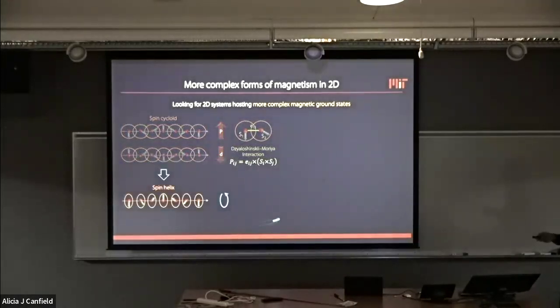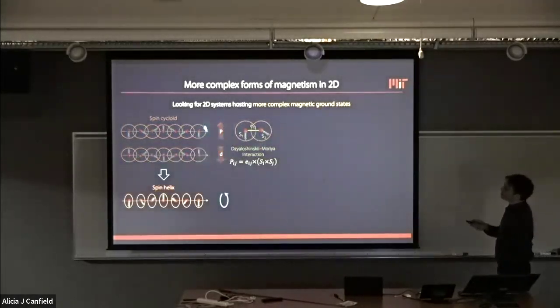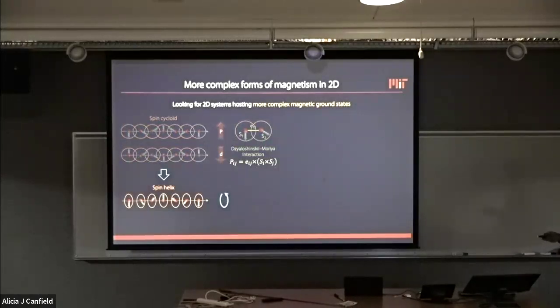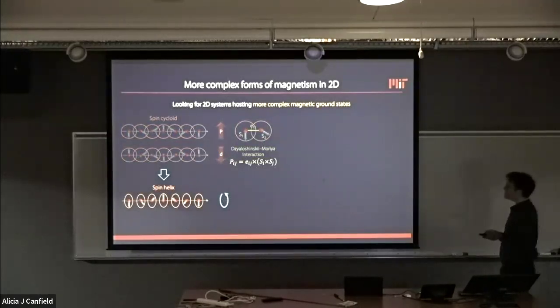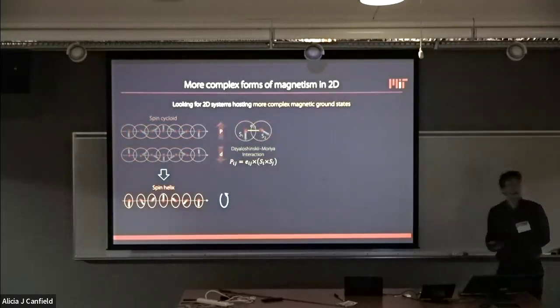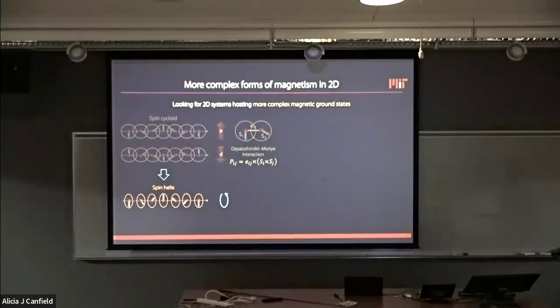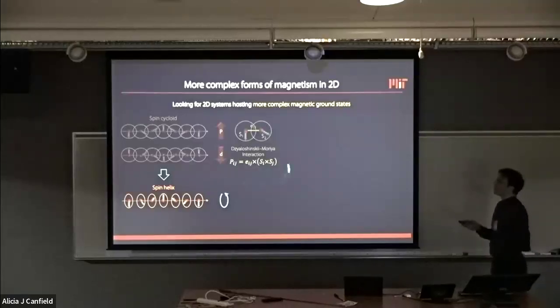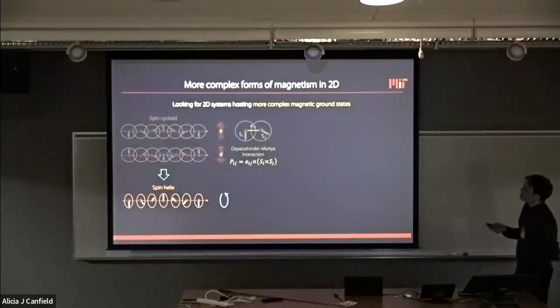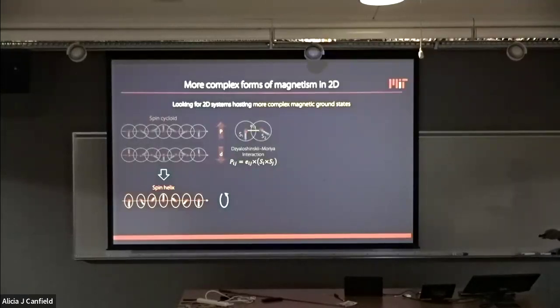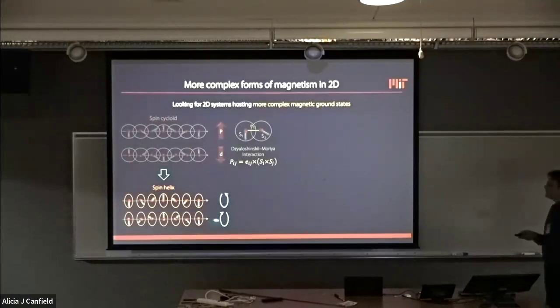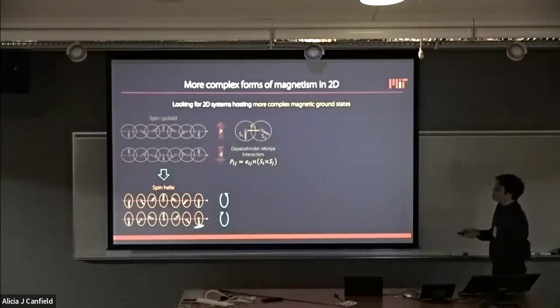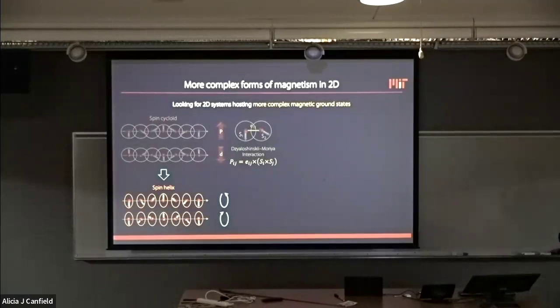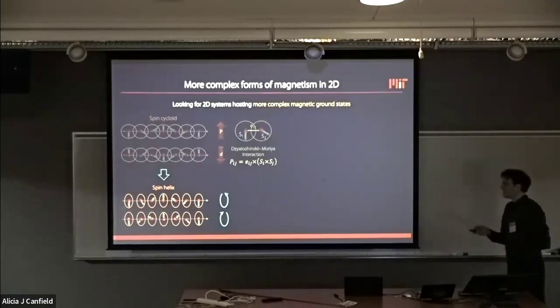Now, another interesting type of non-collinear spin texture, which is actually a very close sibling of the cycloid, is the spin helix. This is also a spin spiral, but now the spin rotation plane is perpendicular to the propagation direction. And that's interesting because the spin helix has chirality. The spin helix state breaks all mirror symmetry, so it's chiral. The cycloid doesn't break all mirror symmetry, so you can still define a handedness, but it's not strictly speaking chiral. Whereas the helix is chiral, and when you switch the chirality, then you break inversion symmetry.